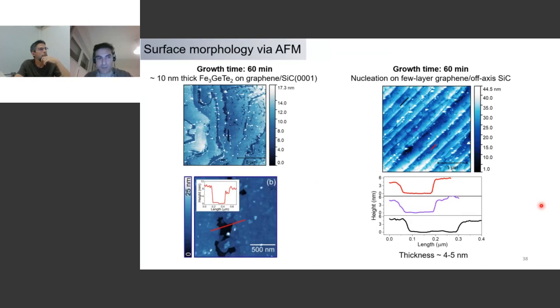Very quickly here about the growth properties. If we grow for 1 hour, we get a 10 nanometer thick iron germanium telluride film on graphene, but AFM shows that we have some holes in the film, like here. And this is exactly where we form this bilayer or few layer thick graphene, right?